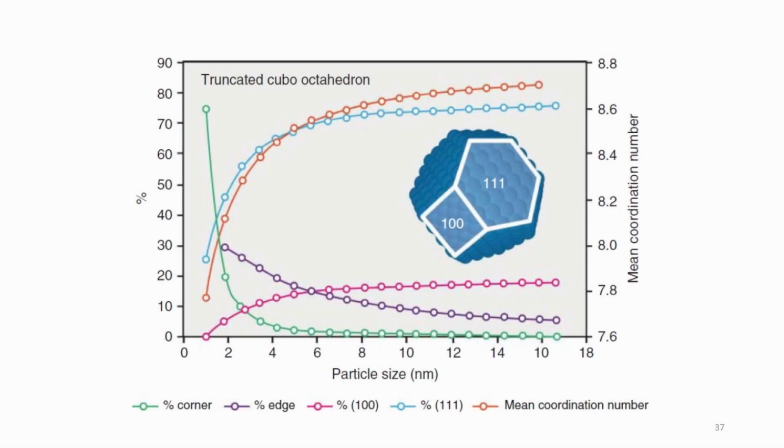Highly dispersed particles expose comparatively more corner and edge atoms than atoms that make up the surface facets. A very important example of this type 2 behavior is found in the activation of methane. Several studies have shown that the rate of steam methane reforming, which is controlled by the activation of the C-H bond, increases strongly with particle dispersion for a wide range of transition metals, including platinum, rhodium, iridium, and palladium.